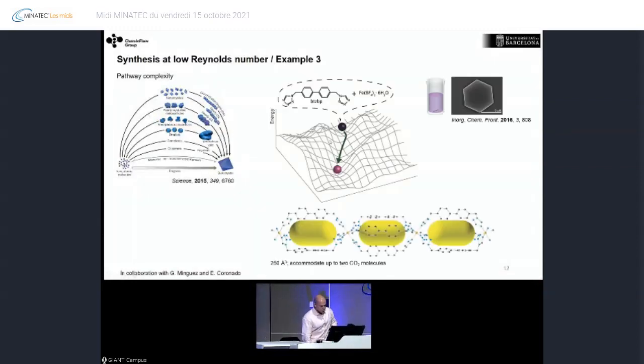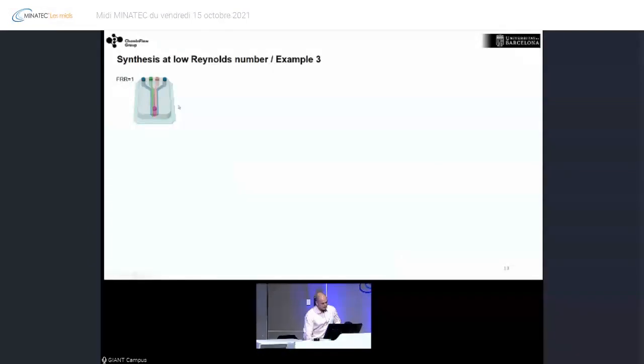So what we did here was the synthesis of this spin crossover, which is also porous, so you see that it can embed up to two CO2 molecules. This is a collaboration with Guillermo Mínguez at the University of Valencia and Eugenio Coronado. And what we did here was the synthesis of this spin crossover with microfluidics.